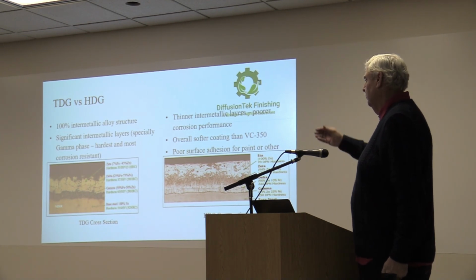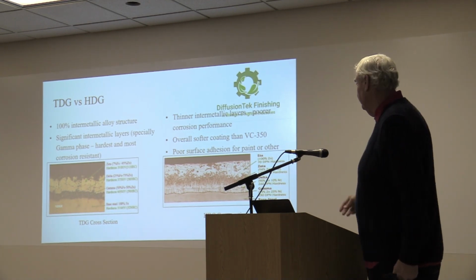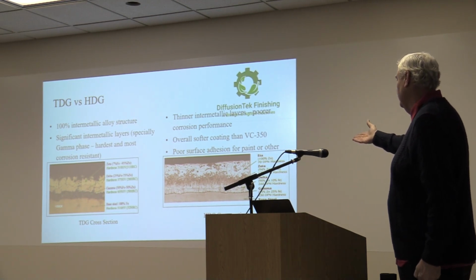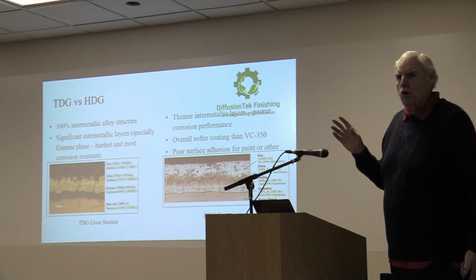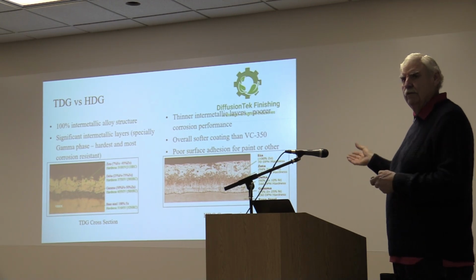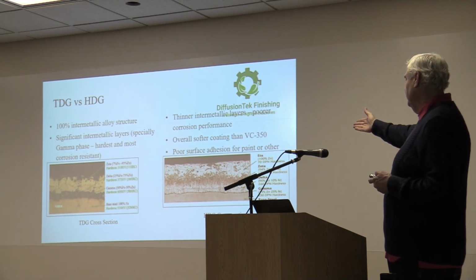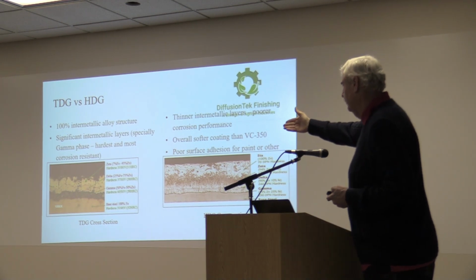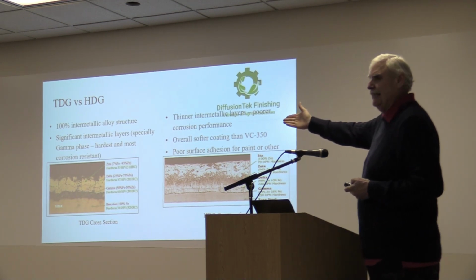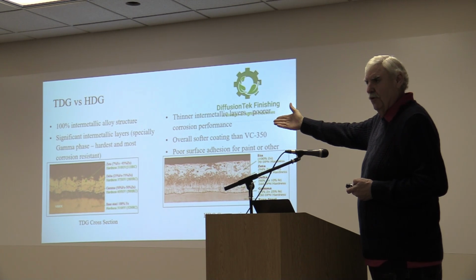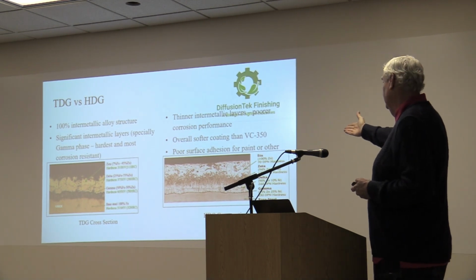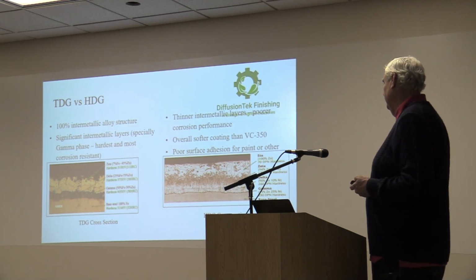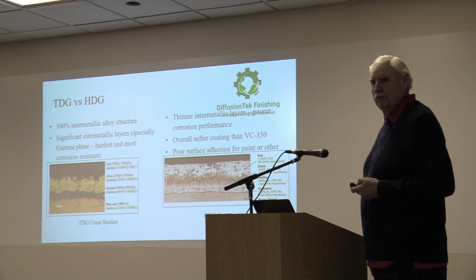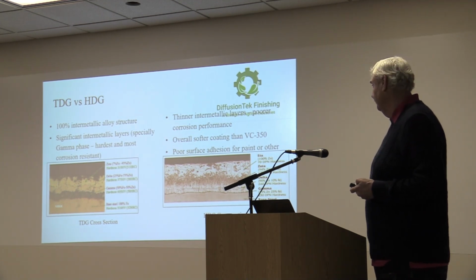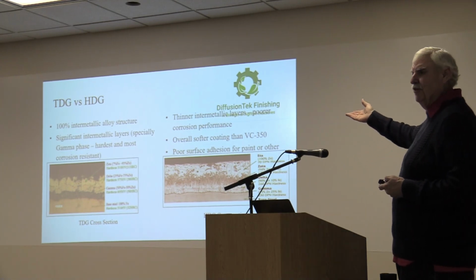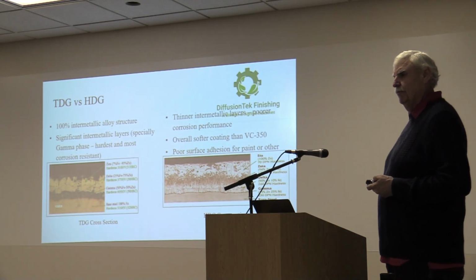But again, thermally diffused down into the steel. You can see some of the same kinds of things over here. So one of the reasons we say, why is ours harder than hot dip galvanized? Well, you can see that upper layer. That's 31 Rockwell C hardness on the thermal diffusion galvanizing. Over here, it doesn't even rate under the Rockwell C scale. Very soft. It's 100% zinc. Very soft, and it will deform.